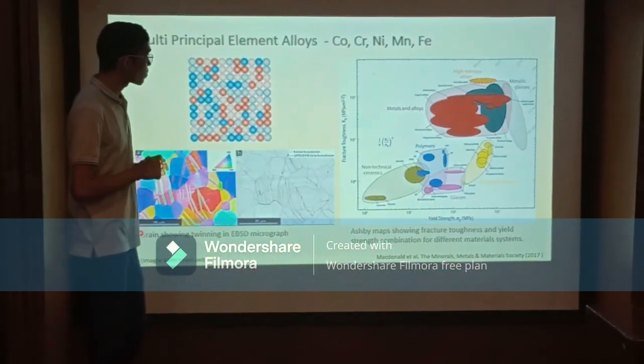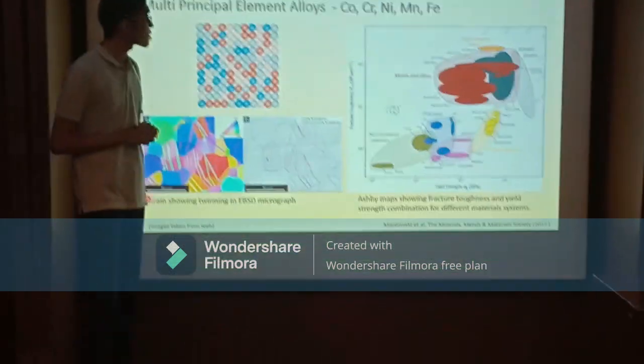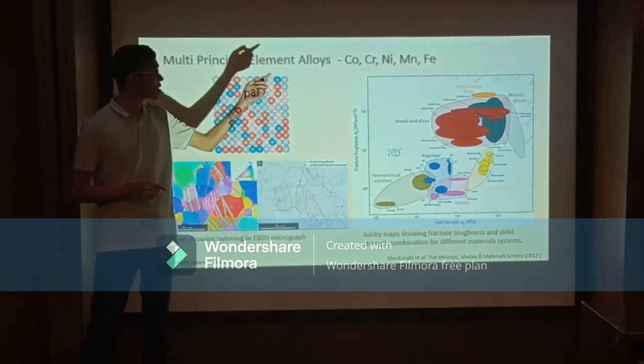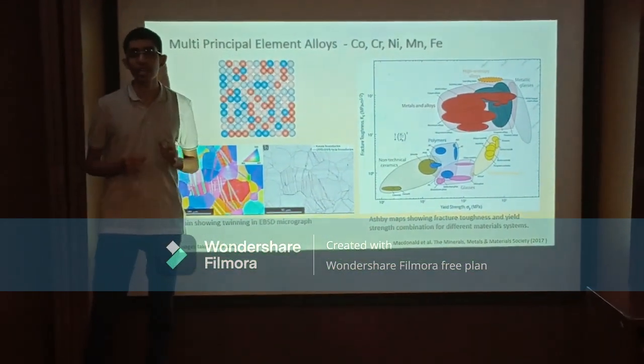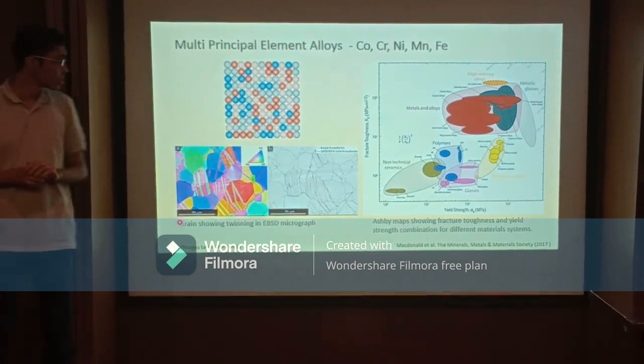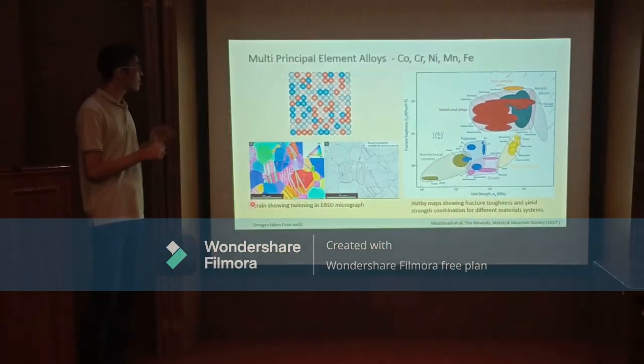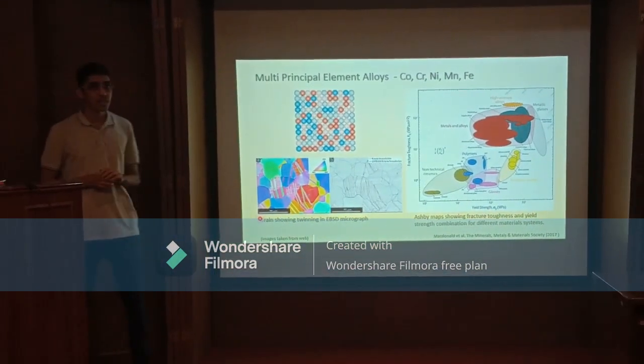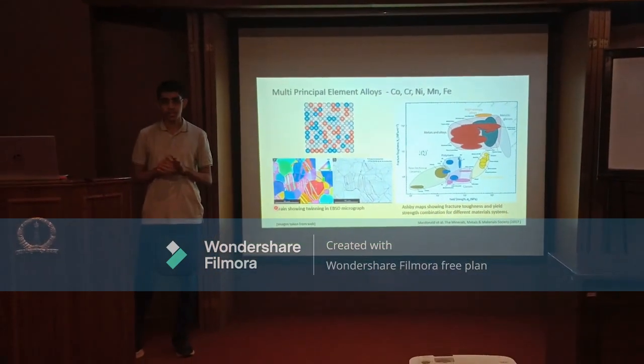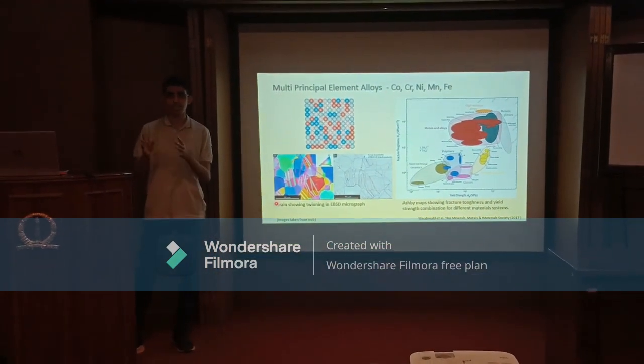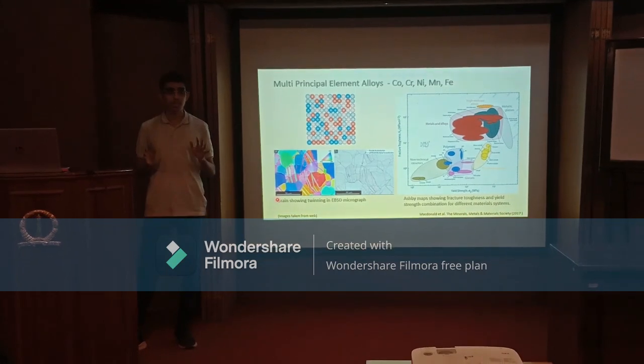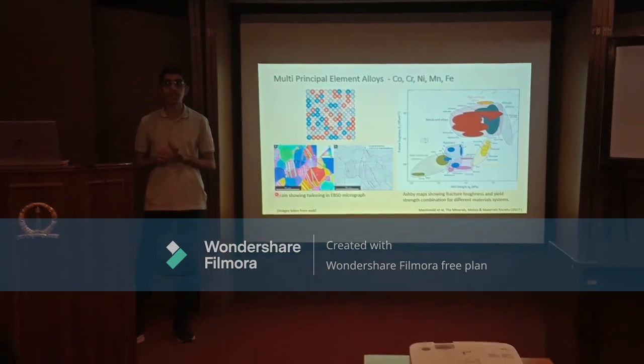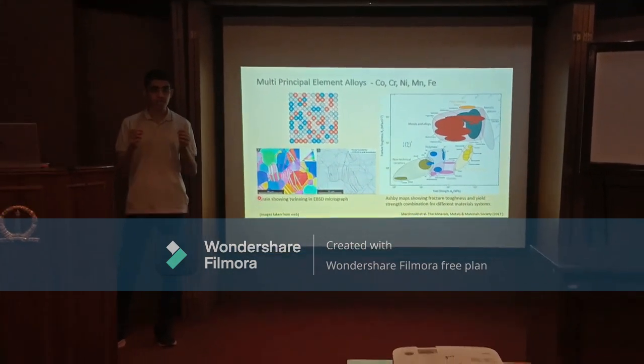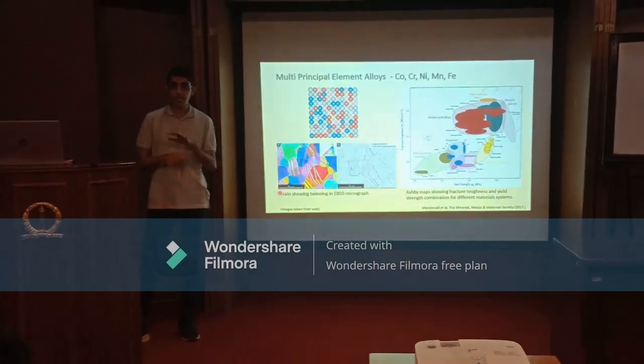So one very popular multi-principal element alloy system is cobalt, chrome, nickel, manganese, iron system, which is also called Cantor's system. So in this particular system we have these 5 elements which are in almost equiatomic ratio, so almost 20% of each. And the amazing thing about this alloy system is that all these elements, even though they are different, they mix up randomly and they form a single phase.